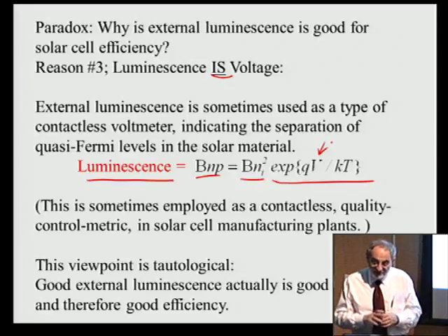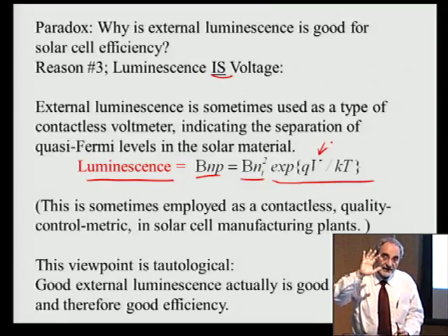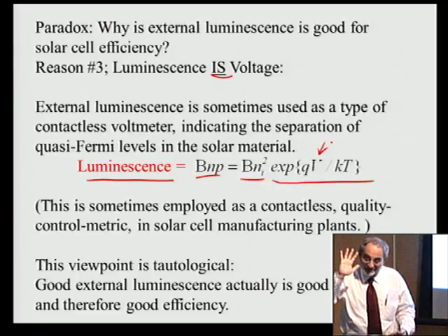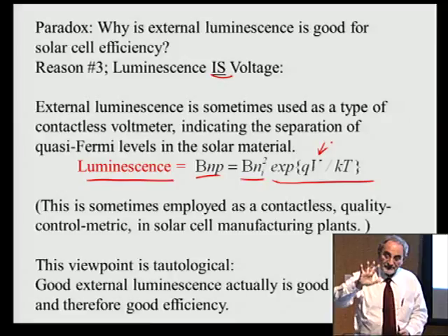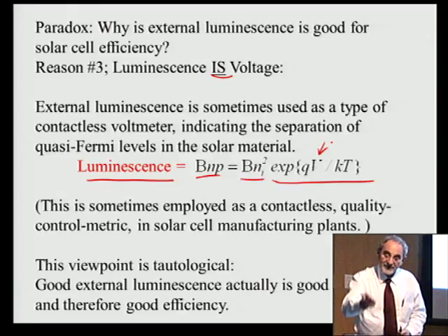We have to have luminescence. And by the way, don't be afraid that you're losing that much. Under ideal optimization, you lose about 2% of the light. It's like charity. Although I hope you give more than 2% to charity. But the solar cell works best when it takes in 90% of the light, delivers it as current, and takes 2% of the light and gives it back as luminescence. That's actually the optimal point of operation.